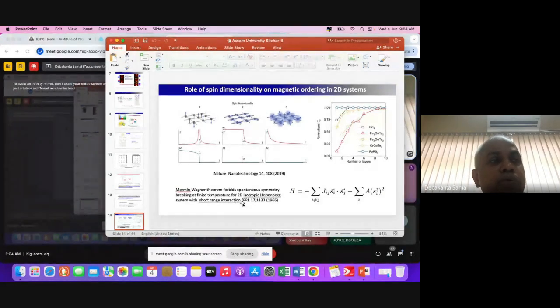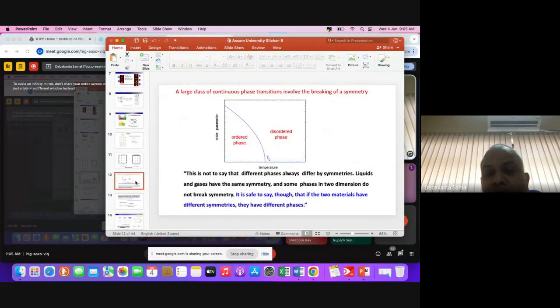So we are considering a two-dimensional lattice like a sheet of paper on which atoms are sitting, and on each atom there is a Heisenberg spin. If this is the case, this theorem tells that you will not have any phase transition. So this is what you see here. There is a two-dimensional lattice, and random Heisenberg spins with Sx, Sy, Sz components. You see there is no magnetization, because we know that if there is a phase transition, as I showed you in the previous graph, you come from a disordered phase to an ordered phase, so your magnetization will shoot up. It will start at the critical point Tc, then it will increase.